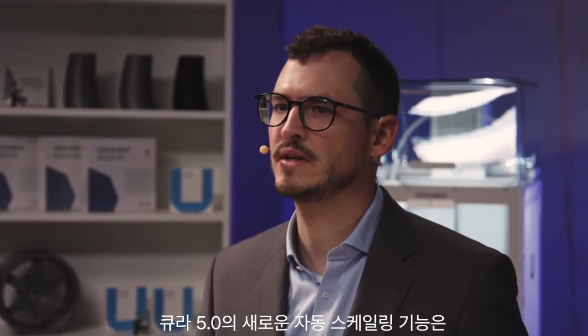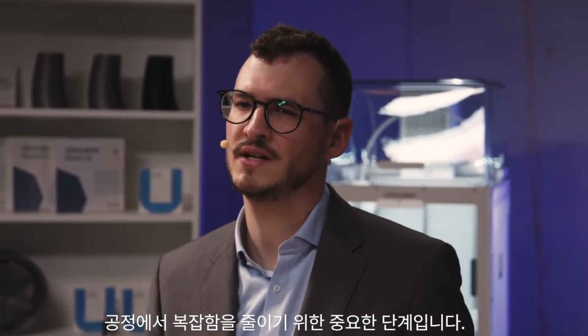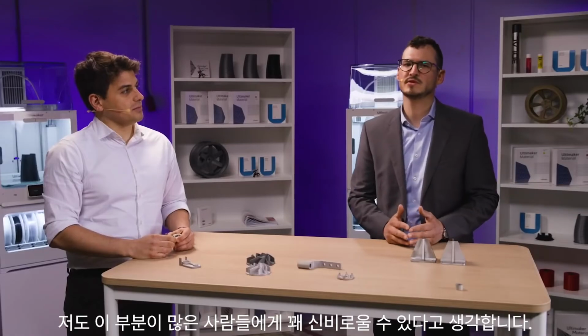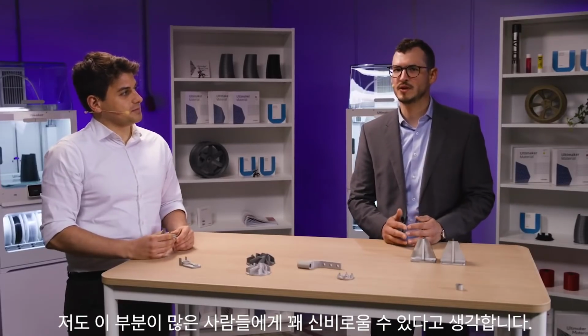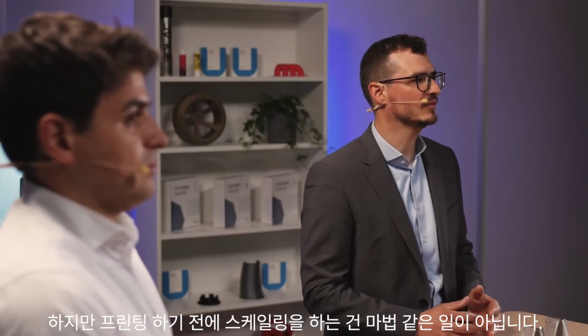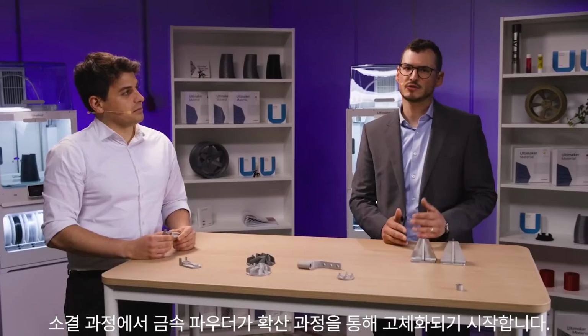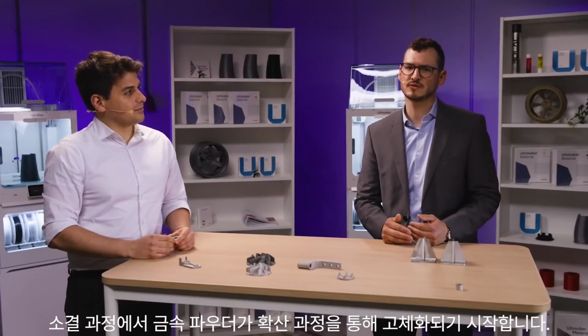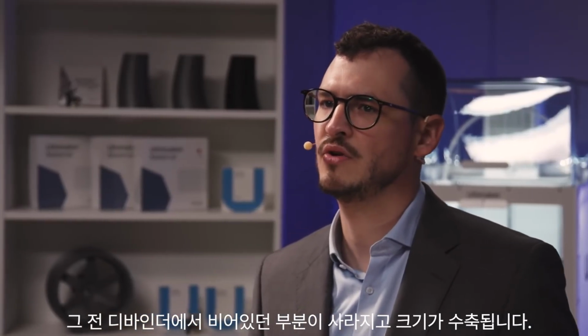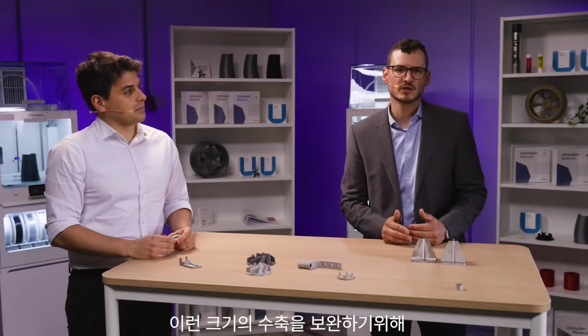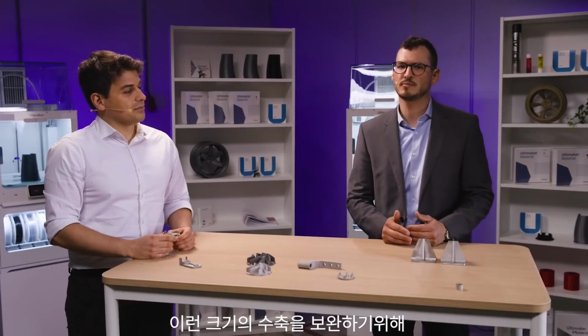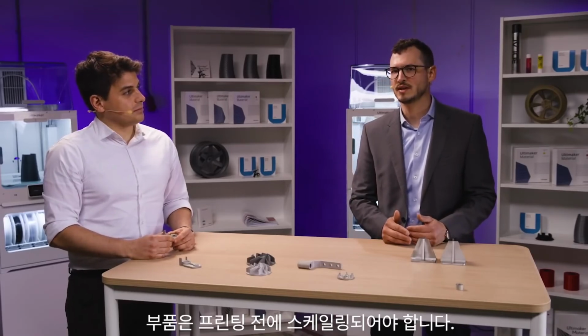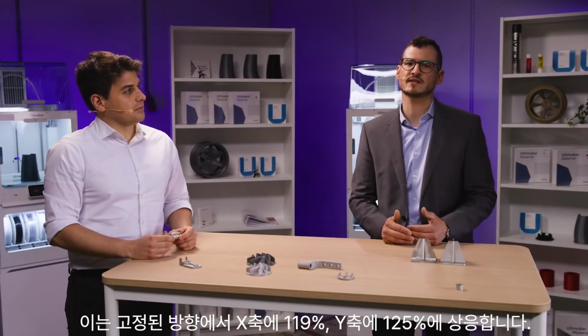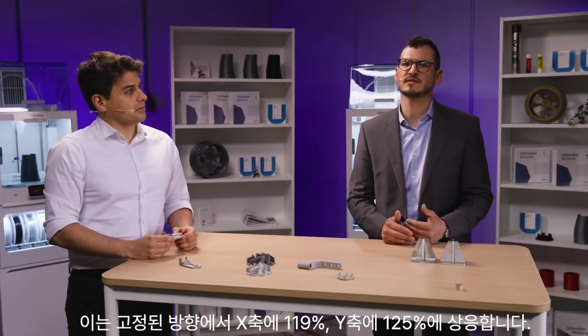The new automatic scaling of the parts in Cura 5.0 is an important step towards the reduction of complexity along the process chain. I know it seems to be mysterious for quite a lot of people, but I can tell you it's not witchcraft scaling the part prior to printing. During the sintering process, the metal powder starts to solidify by diffusional processes. The empty areas of the former binder vanish and the volume contracts, leading to a shrinkage. To compensate for this volumetric contraction, the parts need to be scaled prior to printing. This corresponds to 119% in X and Y and 125% in the Z direction.